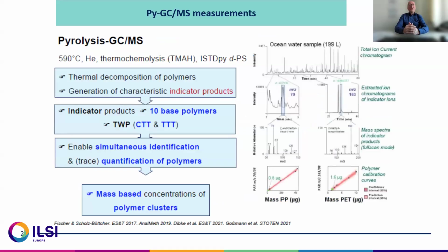How Pyrolysis-GC works is shown here. We have a thermal decomposition of the polymers, and then we have generation of characteristic indicator products. It is not so easy to find the right indicators. On the right side, you see at the beginning a total ion chromatogram. Then you can extract from this the indicator ions for special polymers. From this, you make a mass spectrum with indicator products.